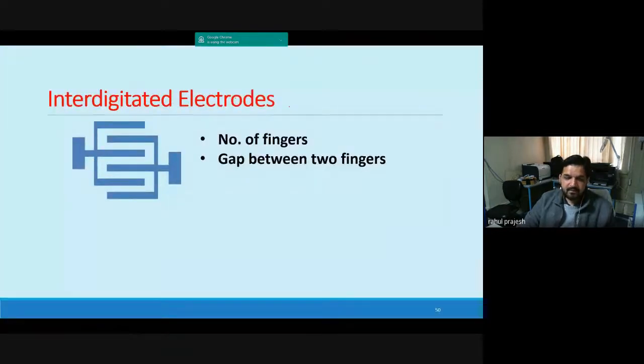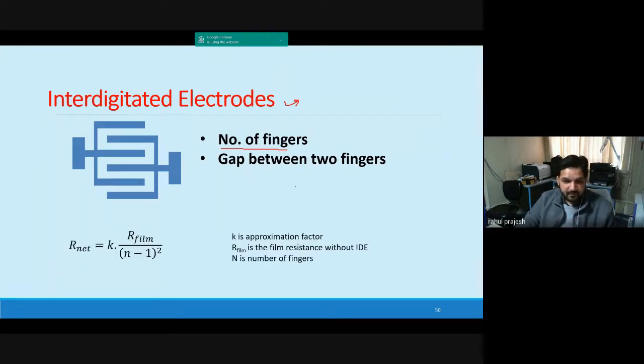Then comes the second part of it, where you have electrodes and sensing film. For electrodes, it is important to consider the number. You need to consider how many fingers there are and what is the gap between two fingers. That's what you need to understand. Most of the time, the effective resistance is the initial film resistance divided by n squared, where n is the number of fingers, because you have multiple parallel resistors, which reduces the resistance. So that's one reason why we use interdigital electrodes.